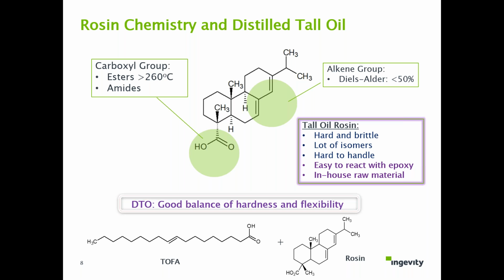And the good thing is the carboxylic acid group is easy to react with the epoxy group at elevated temperature. People know epoxy is a highly reactive functional group that can react with amine, acid, free radical, ionic, almost everything. Also, this rosin is Ingevity's in-house raw material. Again, DTO is a good balance, the hardness from rosin and the flexibility from tall oil fatty acid.